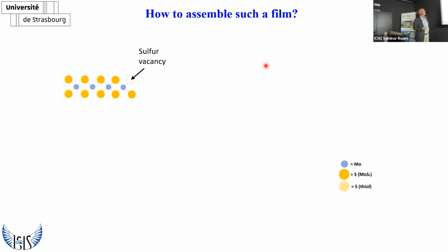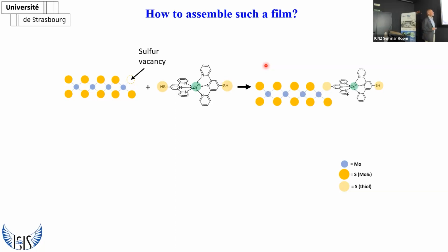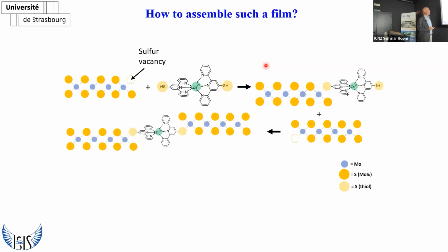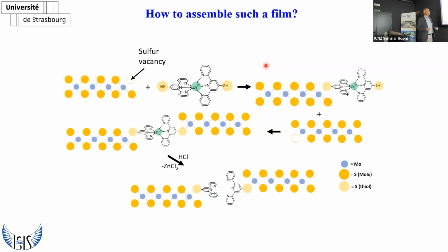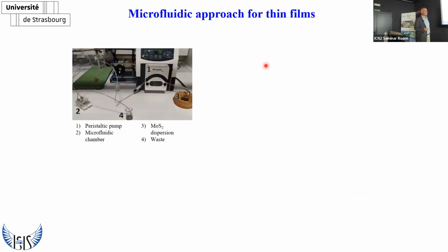because I think it's more interesting to generalize the story. We have sulfur vacancies in the MoS2, and so we added the preformed zinc terpyridine complex, and then once we have created the network, which is something like this, we have treated it with a proton in order to release the zinc ion and to have an empty terpyridine cavity for hosting the new receptor. Okay, you can of course expand this also to other types of analyte.